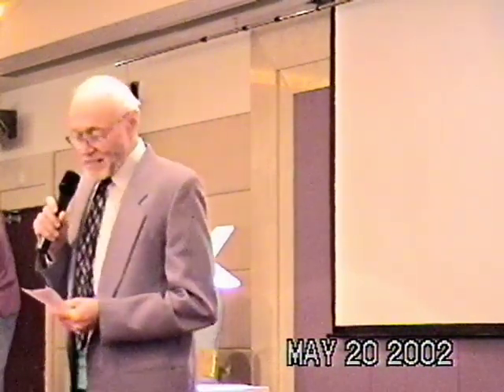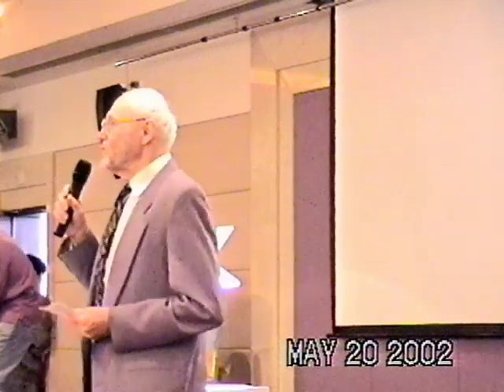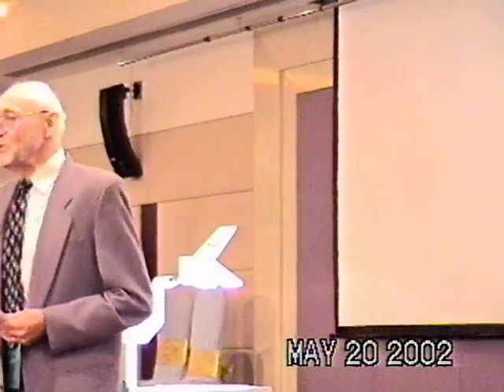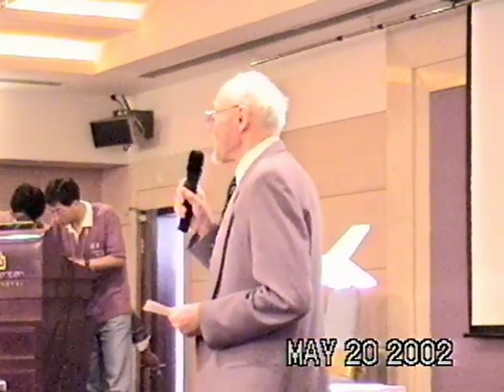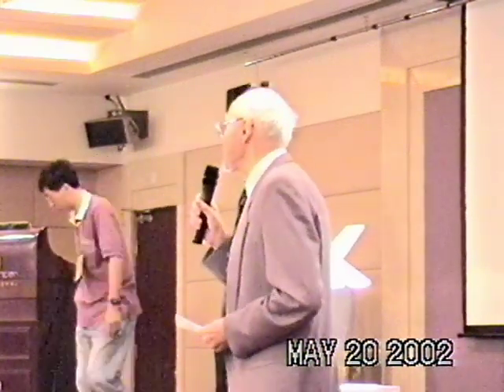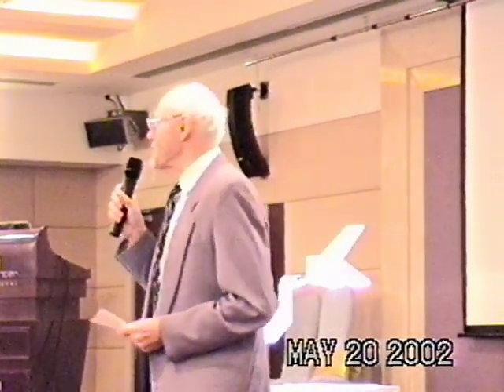I got into this business in the corrosion field, and Mike McCoubrey knows it very well because he was working with us at EPRI, and we found that small quantities of impurities were causing a difference in corrosion that was catastrophic in many cases. And in the process, I looked around in the science field, and I found the people who make field effect transistors at General Electric found that if you had as much as 10 parts per million of sodium in that gate region, they couldn't reproduce the field effect transistors. So when they found that out, they could eventually become successful.